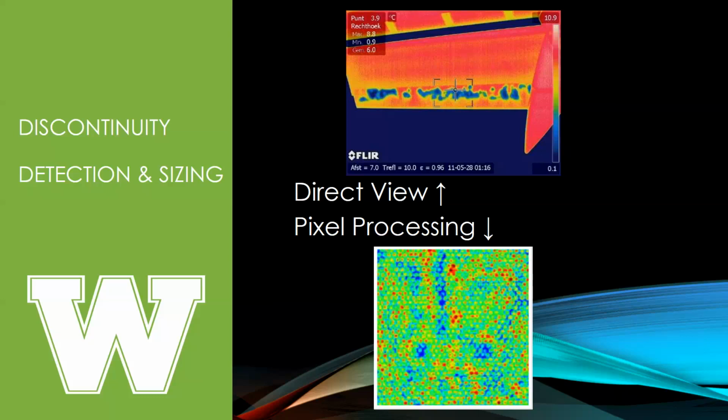So if you image a plane right after it lands, it's warming up, right? The water warms up slower than the structure does because it doesn't transfer the heat as well. Okay, so that water, it may even still be ice. It might freeze in there, and that's part of the reason we want to detect that. Is if you get moisture in a composite and it freezes, it expands. It actually starts to pop the layers of the composite apart.